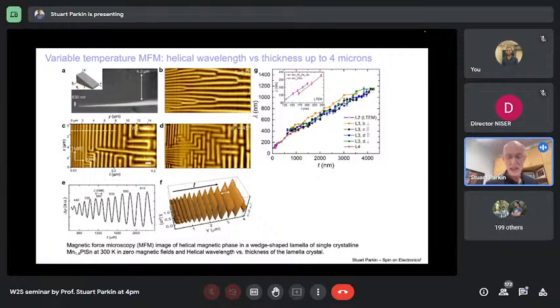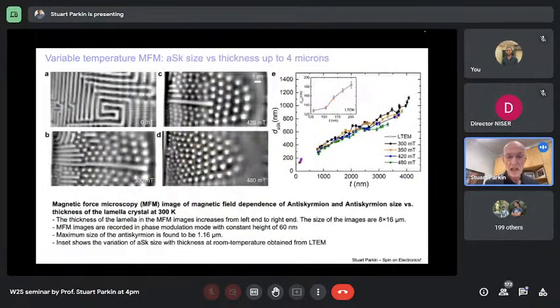This is the first time in any of these skyrmionic systems that such a strong dependence of the helical period was found with thickness. And now, by increasing the perpendicular magnetic field, we switch from the helical state, where again, in the magnetic force microscope, I didn't say, we're looking at the out-of-plane component of magnetization. In the Lorentz images, we look at the in-plane component. Here we look at the out-of-plane component. And so basically, the out-of-plane component goes from up to down, and that's what we see in A.